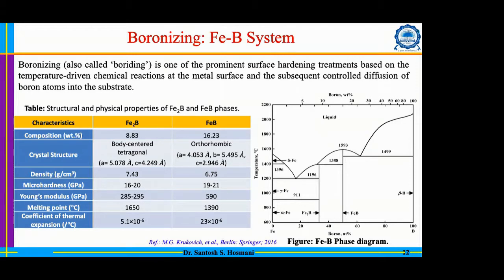If you see the crystal structure, Fe2B has the BCT structure, that is a tetragonal structure, and FeB has the orthorhombic structure. Their lattice parameters are entirely different from the lattice parameters of ferrite as well as austenite. The lattice parameter for ferrite is roughly 0.28 nanometer, or in angstrom, it will be 2.8, and in the case of FCC, it will be roughly 3.5 something. So if you compare these lattice parameters with Fe2B and FeB, they are entirely different. But still, this layer is quite intact during the formation process.